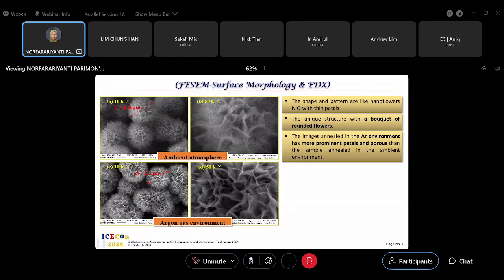For the structural morphological characterization using FESEM, from the figure we can see both samples, annealed in argon and ambient, have a bouquet of rounded flowers, with the shape and pattern of thin petals. But we can see the image annealed in the argon environment has more prominent petals and is more porous than the sample annealed in the ambient environment.